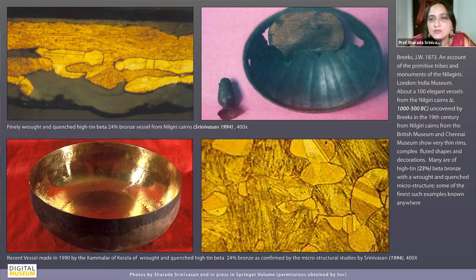And I was also able to find a modern contemporary practice of making these high-tin bronze vessels, because otherwise you might have said there's no real reason why we should think that they should have been made in India. But I've shown that there's a very long-standing ethnographic tradition as well. And you're looking at a vessel which has been recently made, where the ingot at the bottom of about 15 centimeter has been very heavily hot forged and quenched.